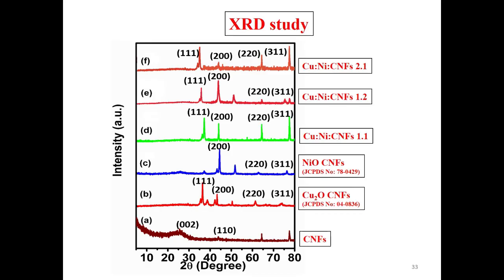This is the XRD study, and here is the ratio we have selected, that is carbon nanofiber, copper cuprous oxide Cu2O carbon nanofibers, then nickel oxide carbon nanofiber, and the combination of copper nickel carbon nanofibers from 1:1, 1:2, 2:1. This is the ratio selected for the synthesis of copper nickel carbon nanofiber. From the XRD study, the presence of the crystal planes suggests the formation of copper nickel carbon nanofiber at different concentrations.